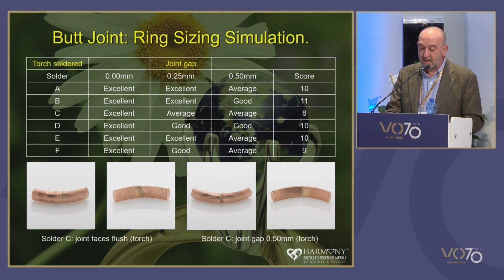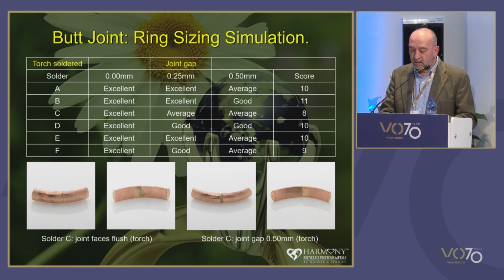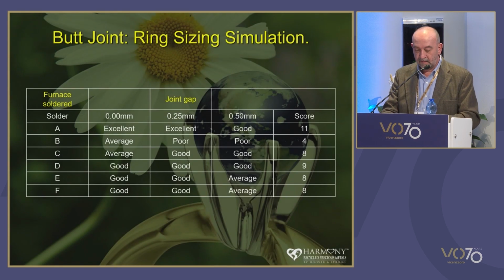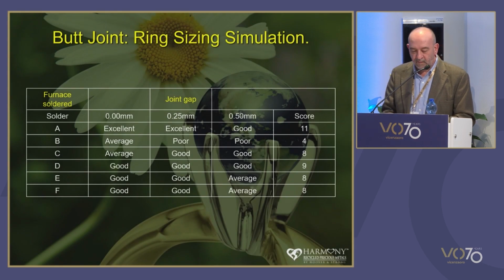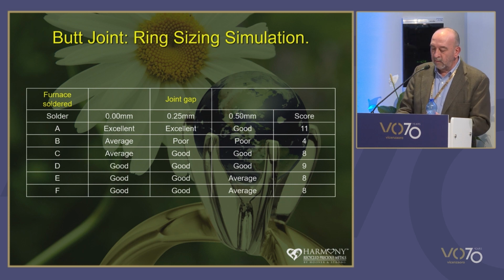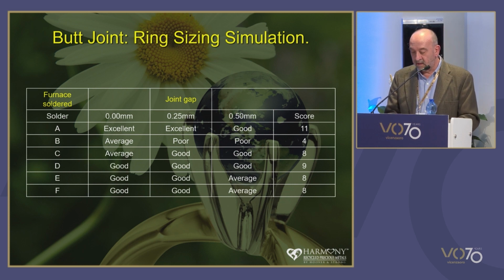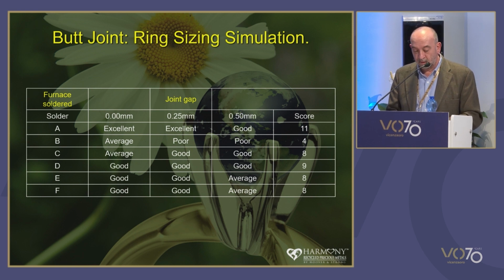And for the furnace tests, only 1 furnace was used, so it was the same belt speed, the same hot zone, we just varied the temperature of the furnace. And these are the results we got for the furnace soldered samples. So overall, they were inferior to the torch solder results. This is evident in the overall lower scores.